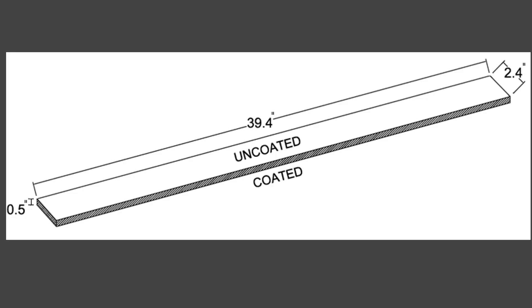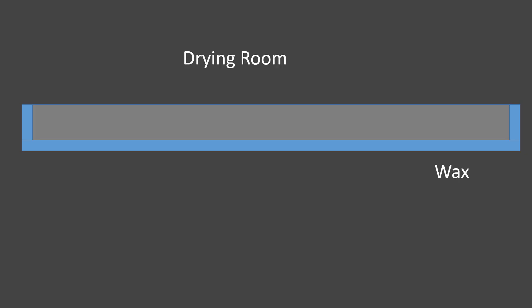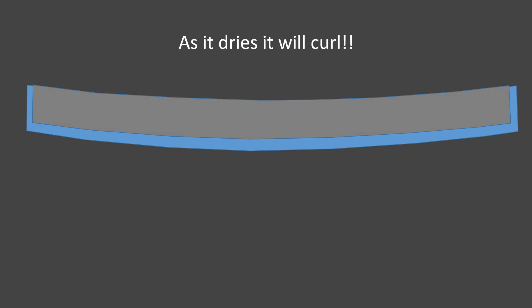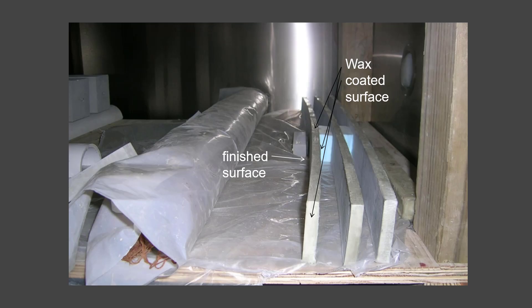This is what an overall sample looks like with its dimensions. Kind of like concrete skis. And this is what it looks like in the drying room. It's got wax on all the sides but right up here that's where the curing compound goes. Then water is going to try to evaporate from the surface. The top is going to try to shrink. We're going to measure what the weight change is but we're also going to measure how much it curls. And if you don't believe me check it out. They curl like bananas.